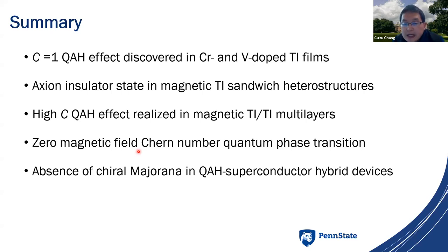And we fabricated the quantum anomalous Hall and superconductor device by performing electrical transport measurement. We found that the half quantized plateau is unlikely induced by the formation of the chiral Majoranas.